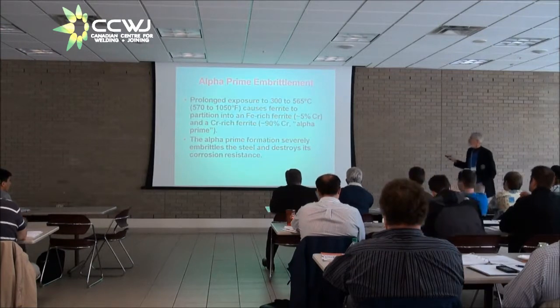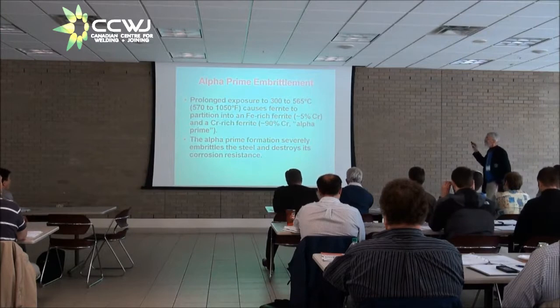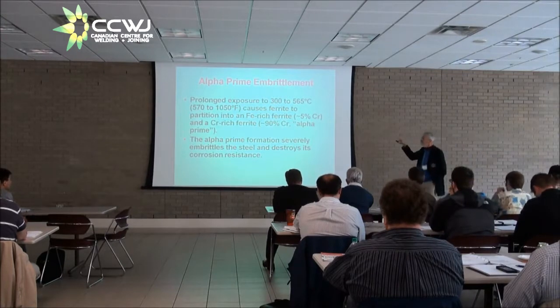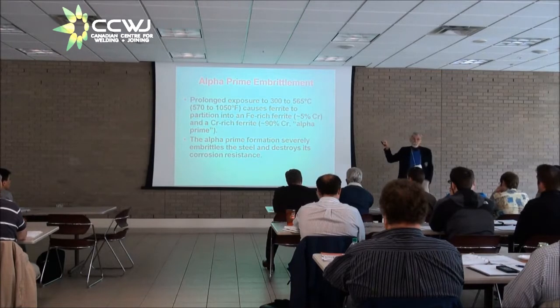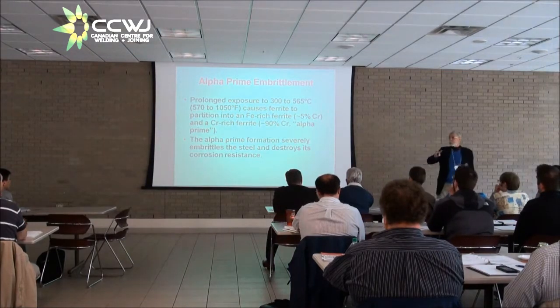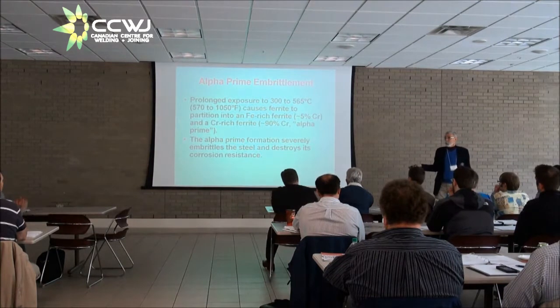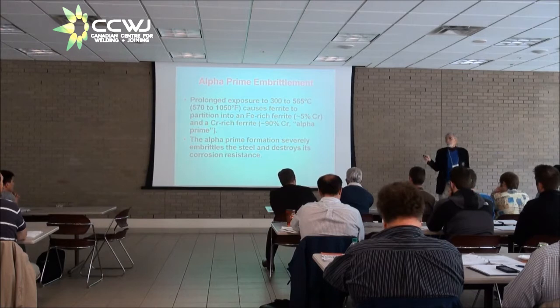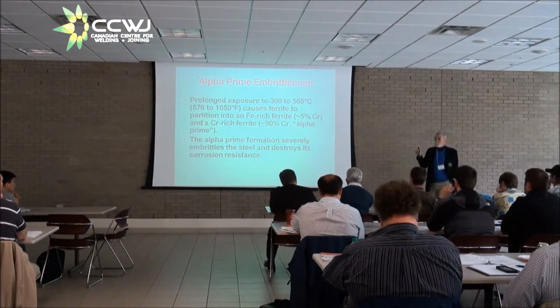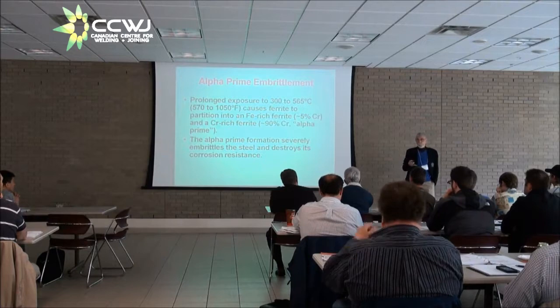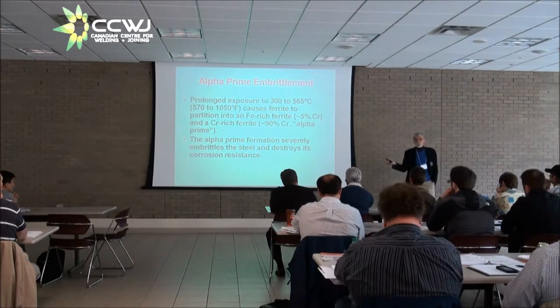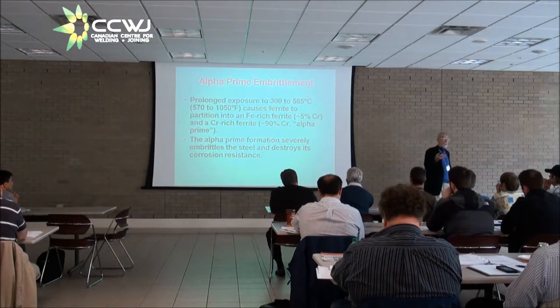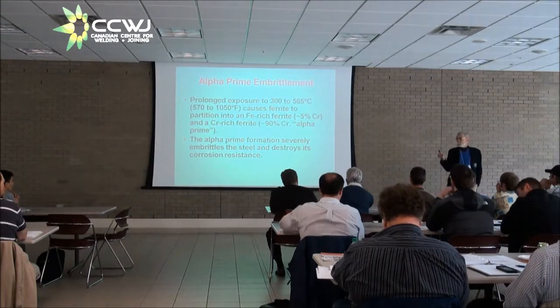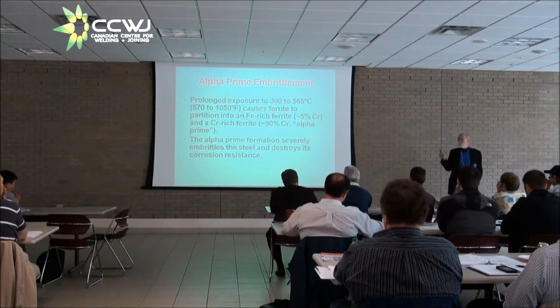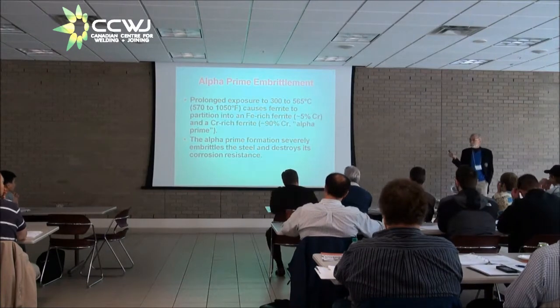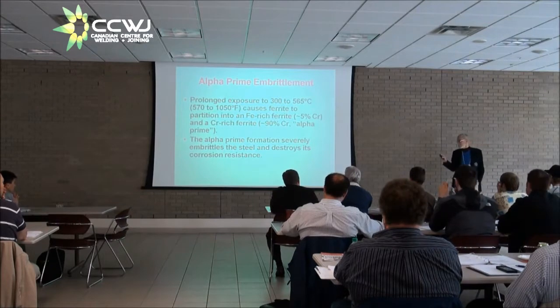Now the alpha prime embrittlement occurs when, not an intermetallic compound, but when ferrite partitions into two ferrites, an iron-rich ferrite and a chromium-rich ferrite. And if you look at the binary iron-chromium phase diagram, what you will see is the two-phase decomposition of ferrite into an iron-rich ferrite and a chromium-rich ferrite. When that occurs, the chromium-rich ferrite contains over 90% chromium. And that horribly depletes the chromium content in the matrix. And so the matrix becomes very susceptible to corrosion.